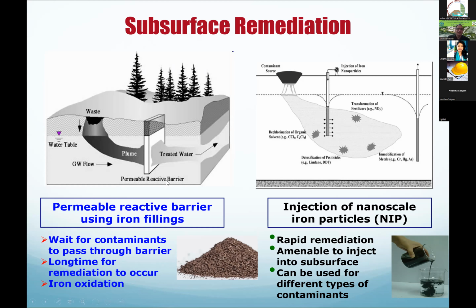It's like tagging the contamination. Whereas here, it's more passive, right? And we cannot inject this one. This is the macro scale. For example, if you have a fine gravel, how can you inject fine gravel into the sand, right? Through a well, you cannot do that. But nanoscale particles, you can. It's a very fine suspension, and you can make the slurry and put it into the well, and you can inject into the contamination zone.